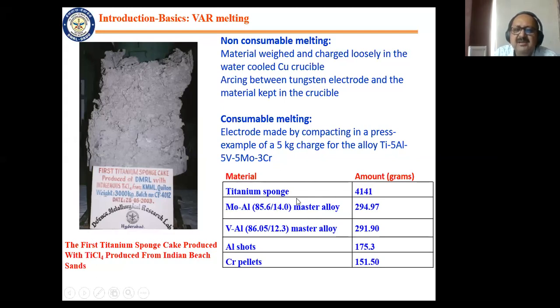The other thing that you do in titanium alloys is, if you look at most of the beta stabilizers, they are either moly, vanadium, iron, or niobium. And all of them have higher melting points as compared to titanium, and they are also denser. So if you add these elements as pure elements, there are chances of segregation, because the melting process itself is part by part. So what you do is you add them as master alloys. Like here we have used moly aluminum master alloy, and we have also used vanadium aluminum master alloy. Then you can add extra aluminum or any other element into this, mix it thoroughly physically, and then press it into an electrode.